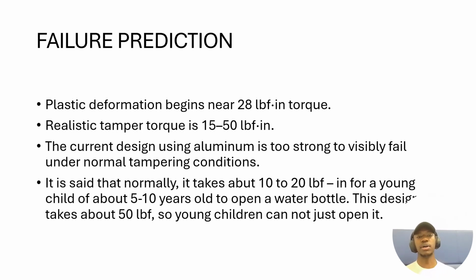In this prototype, I found that plastic deformation begins at about 28 pound-force inch, near 28, not exactly at that. And when I did some research, the realistic tamper torque should be between 15 and 50 pound-force inches, and the 28 pound-force inch torque is right above the strength of most 5 or 10-year-old children, who typically apply between 10 to 20 pound-force inch when opening normal water bottles. So this makes the design child resistant, because it's a little bit higher than what they can normally open.